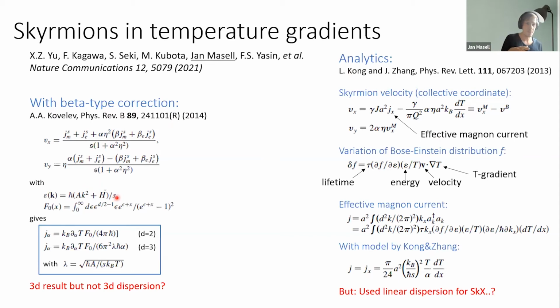So now we're considering isolated skyrmions in the ferromagnetic background. What he could do was to boil this all down to one dimensionless integral that has to be solved, and gives you the magnon current in 2D and in 3D. A thin slab which is of the order of one skyrmion size thick, which is what we usually have in experiment, is already in the 3D limit.